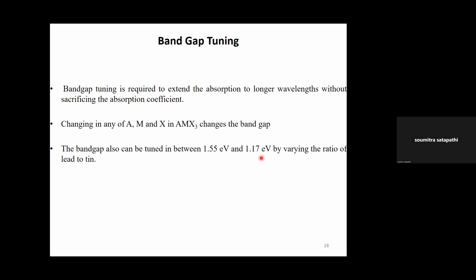Okay, I want to make a solar cell which will be able to absorb in the visible range and also in the UV range and the near IR range. I simply tune the band gap. So then I can get different absorption at different wavelengths. That is possible in the case of the same material, the perovskite. So that is the uniqueness of this material. I want to make a laser out of it, I can do that too. But whether you want to make a laser or solar cells or LED,